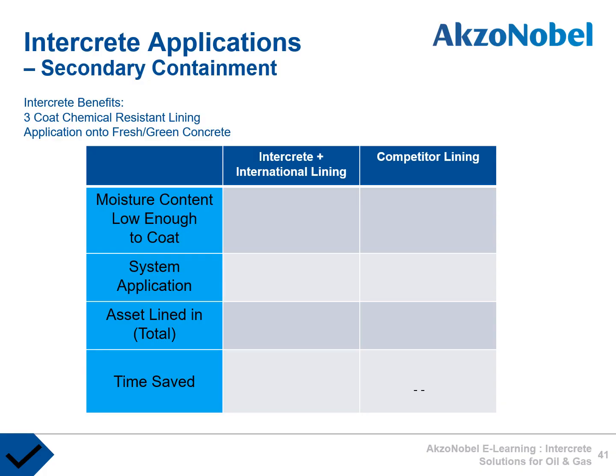In this example, we compare the application of one of our chemical-resistant linings with a competitor system with an equal number of coats. The timescale starts from pouring the fresh concrete to create the bund. Both systems need the moisture content to be low enough to accept the coating. Using Intercrete under the chemical-resistant lining, we can go on in 24 hours after the pour. The competitor lining will need to wait 28 days for the concrete moisture to get down to 4% or below. The system application, Intercrete with the international lining, 4 days. Competitor lining, 3 days. We take an extra day obviously because we have the Intercrete coat added.